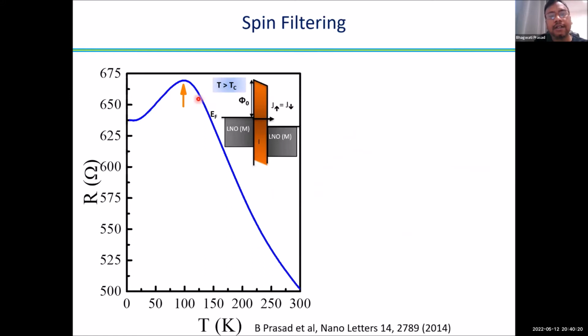Now let's understand this. Above the TC, this barrier is just a normal insulator. It's a paramagnetic insulator barrier, so basically we can say it's metal-insulator-metal. Now, why is the resistance increasing weakly with decreasing temperature? Because the barrier height is not that large, so there is thermionic emission. That means electrons classically move over the top of the barrier. This happens more at room temperature. But when you decrease the temperature, you reduce the thermionic emission. As a result, the resistance increases.